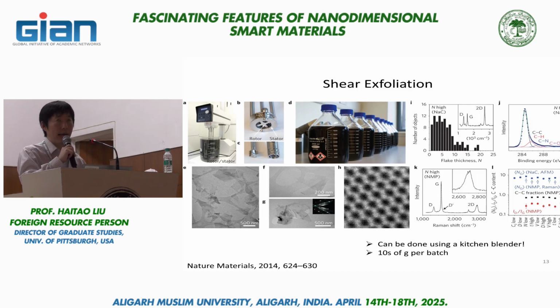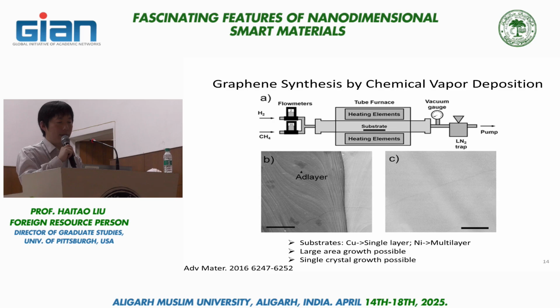Okay. So what happens in the chemical vapor deposition is you have a furnace in the middle, and there's also a substrate, usually metal. And the two most common substrates used in graphene synthesis are copper or nickel, or some alloy of those metals. So during this process, you heat up the metal to about 1,000 degrees Celsius, and you flow precursor gas. The most common precursor gas is methane, mixed with hydrogen. There's a decomposition of methane in the gas phase, and there will be some kind of process happening magically on the metal, and eventually you get a coating of single layer graphene on those metals.